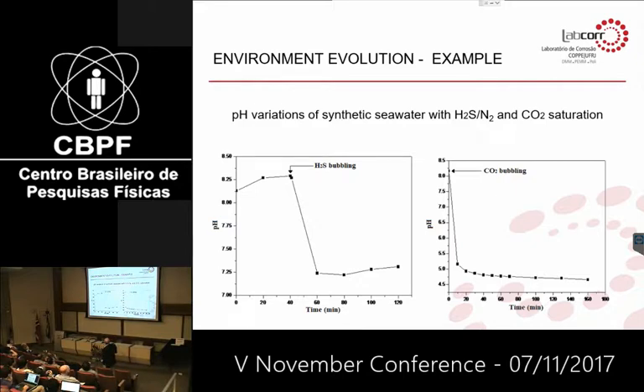In this case, we can see how complicated the simulation of seawater is, seawater containing a mixture of nitrogen and H2S. The pH of seawater is 8 and goes to 7.5. In terms of corrosion, it's not very, very critical, but the threat of localized corrosion is very important. And the same environment with CO2. So CO2 makes the pH much more acid. So we cannot define in a simple way which environment is much more aggressive for the material, depending on other aspects.